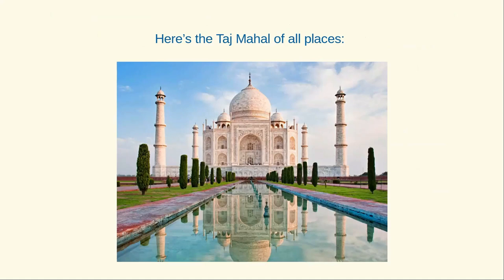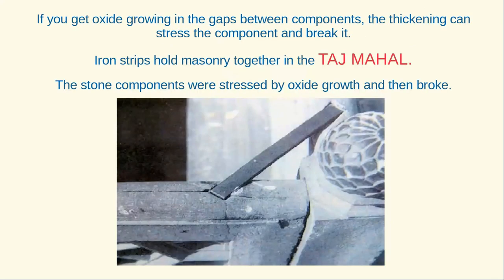Here's the Taj Mahal of all places. If you get oxide growing in the gaps between components, the thickening can stress the component and break it. Iron strips hold masonry together in the Taj Mahal. The stone components were stressed by oxide growth and then broke. Here, where the iron goes into the stone, oxide grows and it's cracked the stone. So you think that oxide or rust just takes away metal, but it does more than that if it's at an interface.